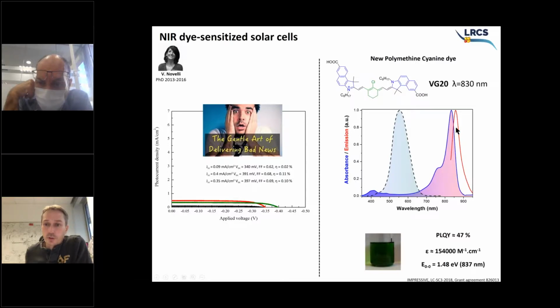Okay, and where it's beautiful is that the main absorption band, the S0 S1 transition, singlet to singlet transition, is very, very strong in the near infrared, as often happens in many dyes. We always have a contribution in the blue, but these very small S0 SN transitions in the blue are just a little bit apart from the photopic response. So in solution, what you will see is this green color. It is a green dye which has a photoluminescence